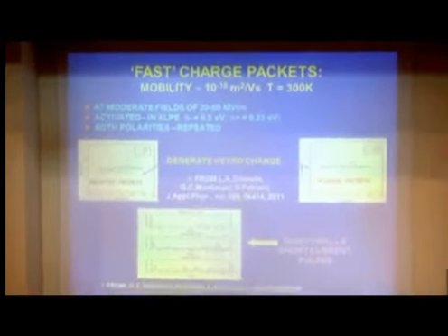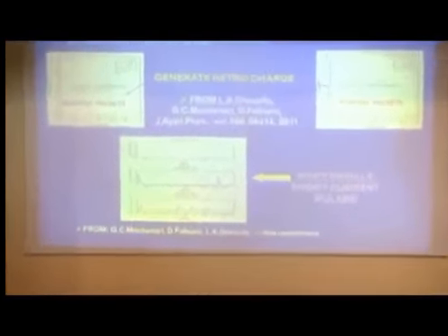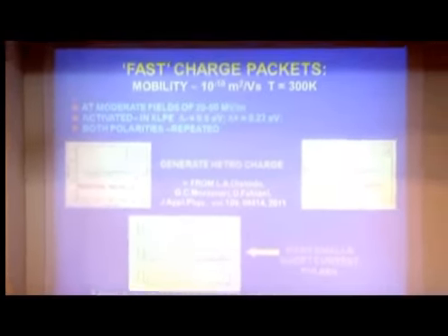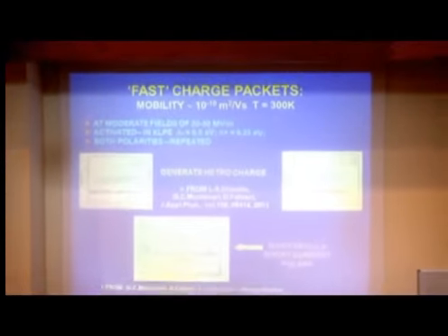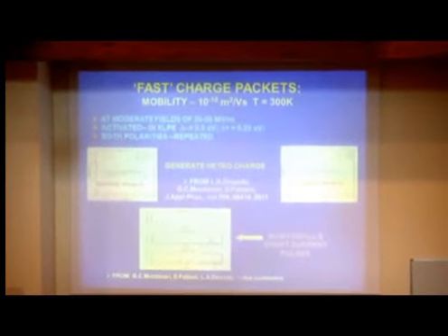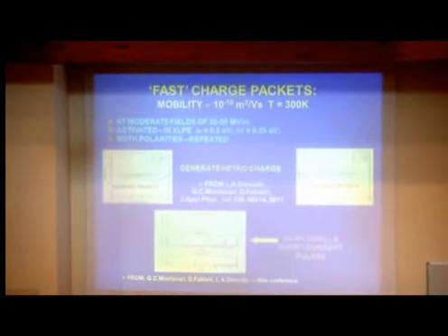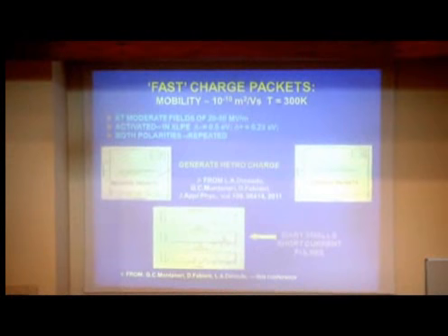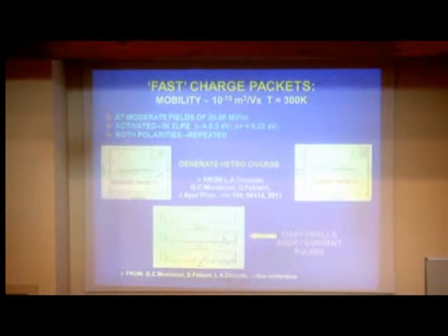And recently we've been able to identify the current pulses associated with these packets. There are many small current pulses. And these packets are delayed in their extraction, and they give a small amount of heterocharge, both positive and negative heterocharge, almost as soon as you've switched on the material, because the packets start very quickly and they travel very fast. So this is an important feature.